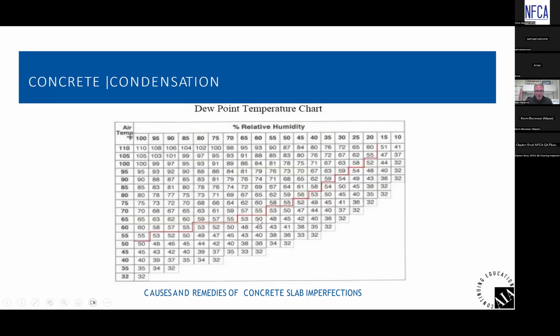I don't know if you can see my cursor. We can. You can? Okay, so just for example, we'll do 70 and 50 because those are two common values. So 70 degrees temperature, 50% ambient humidity. In order for condensation to occur, I need a substrate temperature of about 50 degrees. So you're very far away from dew point if we're in an acclimated space, because we're acclimated and we're at 70 and 50, the chances of the concrete slab being at 50 degrees are probably slim to none. But when you're not acclimated, that's when you can fight with condensation.